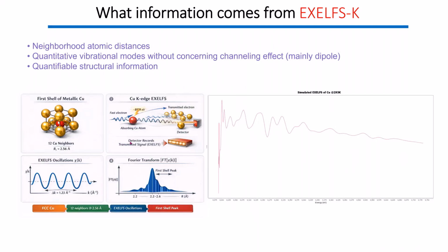But you also can get the quantitative vibration mode without concerning much of the channeling effect, which you often encounter with the elastic scattering or any other L edge or M edge, because the K edge effect is mainly dipole, and there might sometimes be a bit of a quadrupole effect. But in most cases, the channeling effect you basically can ignore. So in that sense, it's more quantifiable structural information, although it turns out it's quite complicated to quantify. But in terms of quantifiability, it's slightly cleaner to do so.